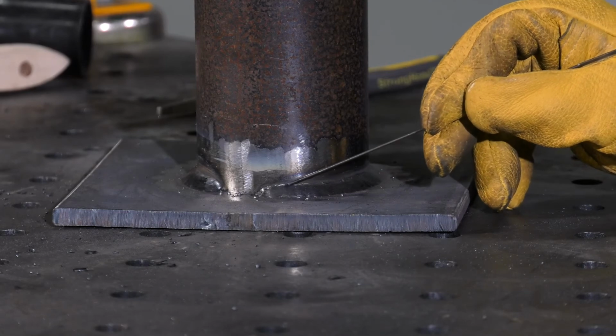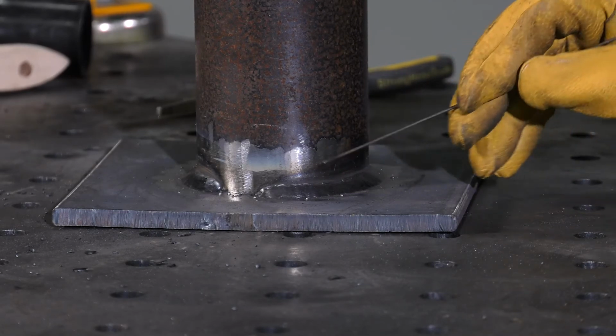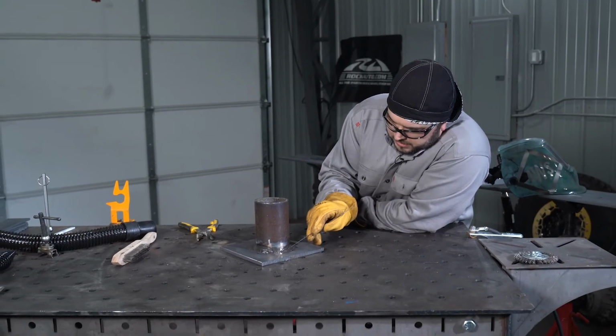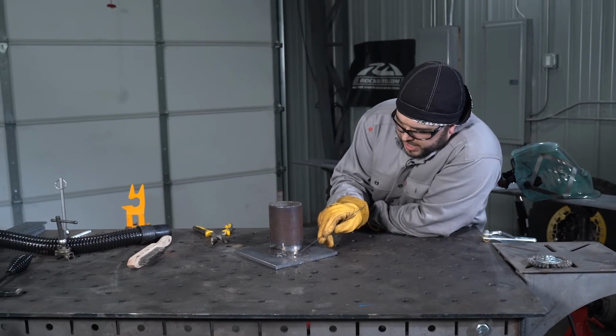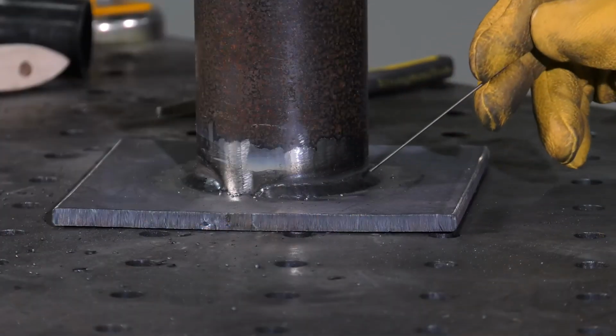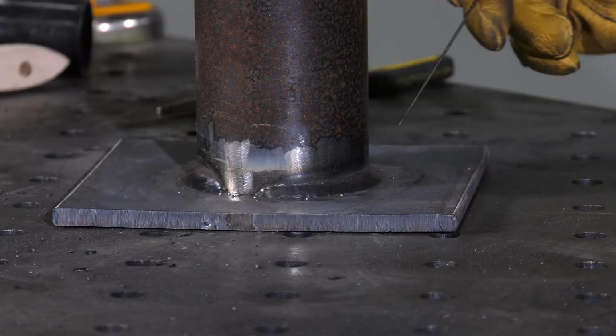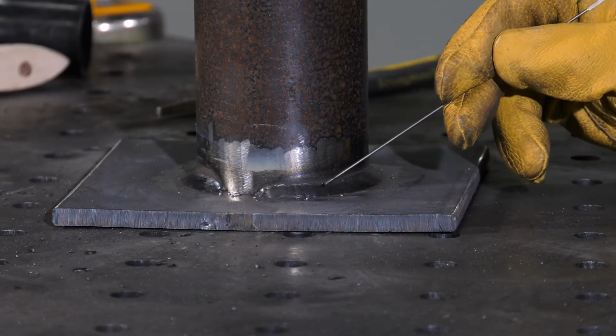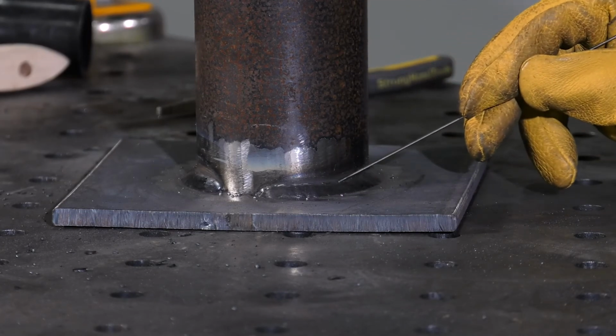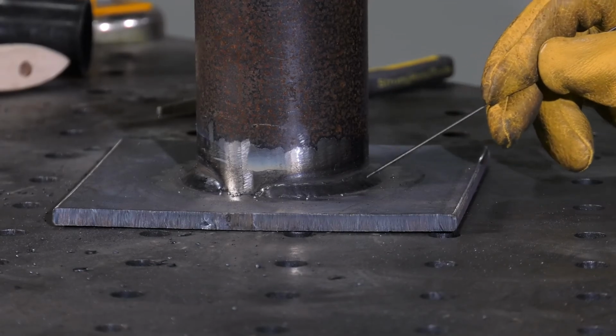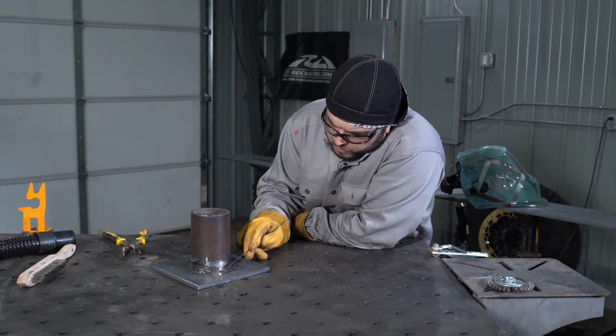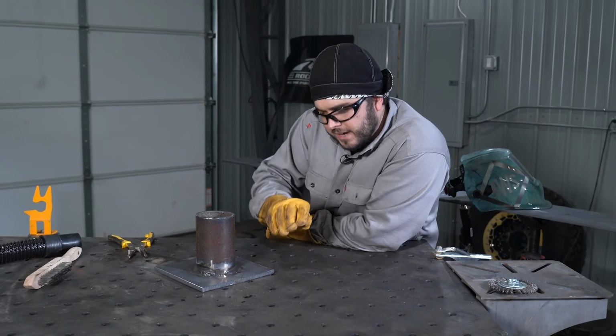Here we have a great example of a fillet weld around pipe. What we want to do to achieve a weld like this is maintain a nice drag angle while we move across the radius of the pipe. We always want to make sure that we're looking at the toes of the weld while welding, that we're not getting undercut, and we want to make sure that the profile of the weld is convex.